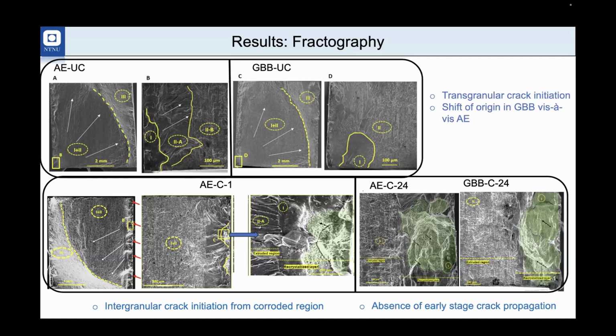On the other hand, if you compare these results with the corroded conditions, you'll see that even for 1 hour corrosion duration, where the maximum corrosion depth may not be high, there are multiple crack initiation sites. And contrary to a transgranular crack initiation, you can see intergranular crack initiation because the intergranular crack is already formed as a result of the prior corrosion. If you compare these results with that of a 24-hour corrosion duration, how does it change?